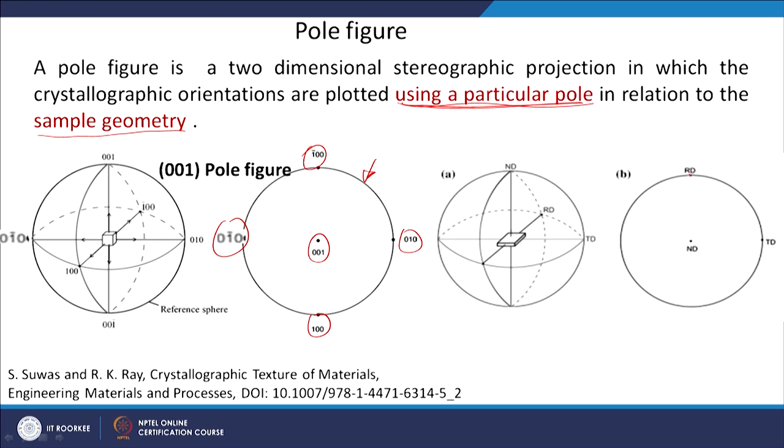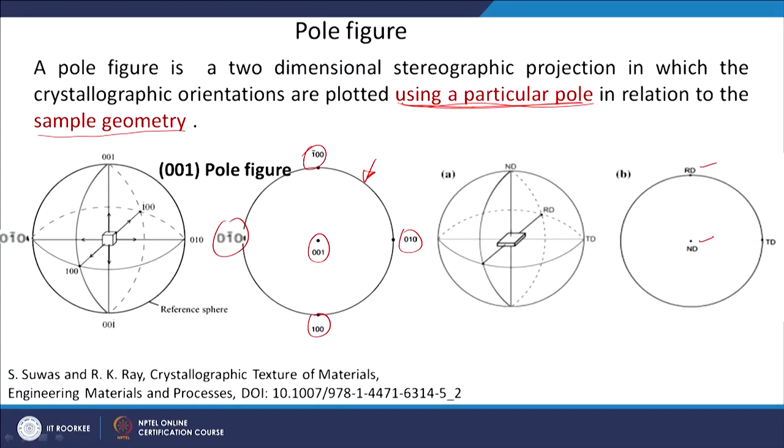So you have a rolling direction here, the normal direction is just hitting the top pole, so it is exactly at the center, and the transverse direction is at 90 degrees to both RD and ND. So this is the sample geometry, and now with reference to this we will be able to tell what is the orientation of each grain. So like we did just for HKL UVW, similarly you can do in pole figure, that this is my sample geometry, this is my RD, ND and TD. With reference to this, for example, if I want to plot 001 pole figure,